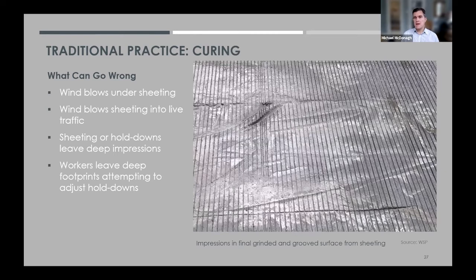If too much wind blows under the sheeting, now you're rendering it ineffective in terms of preventing moisture loss. It can also blow your sheeting into live traffic if you have a staged construction site. And then there's also a risk of it leaving impressions in the UHPC. In this photo here, you can see a number of deep impressions that exist even after the UHPC overlay was ground and grooved. And finally, there are a number of documented cases of workers who venture out onto the UHPC, probably to adjust the hold downs if the wind kicked up, thinking it could hold their weight, and then they end up leaving footprints.